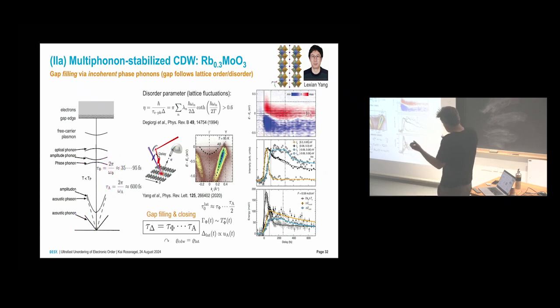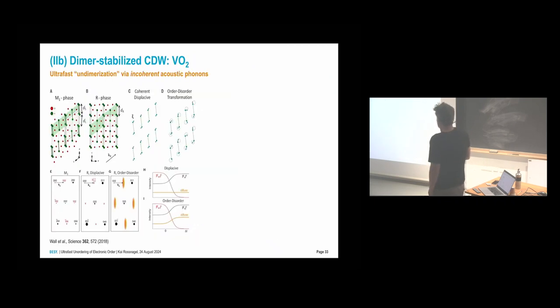Here again we have that the charge density is mostly given by the lattice charge density, but now we start to vibrate this lattice in a fast way and thereby introduce incoherence in the system and fill the gap. There is then a relation to VO2, where you have the dimers and where Simon Wall has studied this with ultrafast X-ray diffraction. He also made the point that on the very fastest time scale and with strong pumping, this is not a coherent displacive transition where all the atoms move coherently, but an order-disorder transformation, which you can see in the experiment through the occurrence of diffuse intensity. Diffuse intensity is again an indication of breaking of long-range coherence.